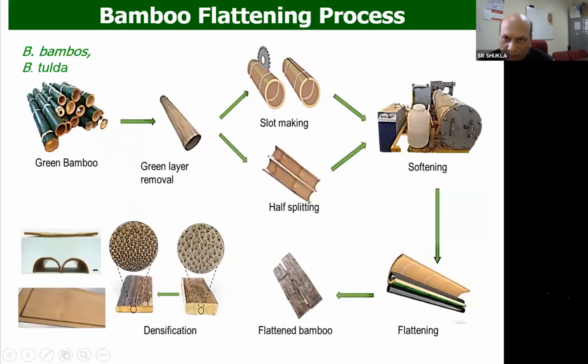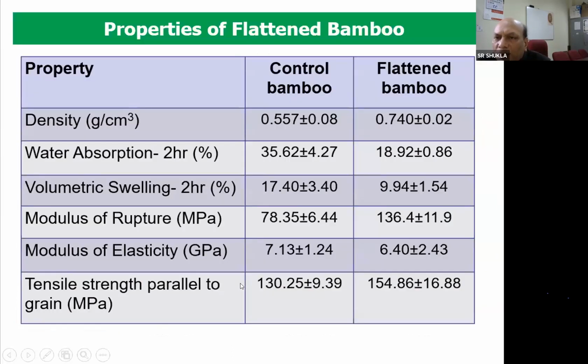Like, so these are the bamboo, green bamboo. We have to remove the outer skin because it's very hard, and when we try to flatten it, the cracks will come in. So after that, we have to make a small slot in the bamboo like this, and then using steam we can soften the bamboo, and then using the roller the bamboo can be flattened, and this is the flattened bamboo, and then different layers of the bamboo veneers can be put together, and they can be densified using the hot press.